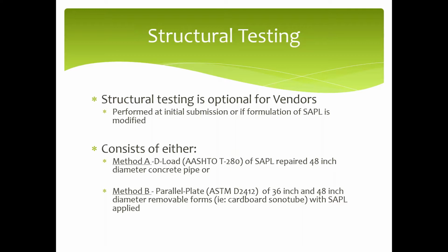And Method B is what we call the parallel plate test. It's a test generally applied to a more flexible material, and we apply it in a 36-inch and a 48-inch removable form. That's what we deemed in the work plan, which really we were thinking of as cardboard sonotubes when we were thinking this through. They would apply their liner material in there, we let it cure, and then we do the parallel plate test, which basically deforms the pipe vertically by at least 20%. Then we see if there are any deformations or issues during that deflection.